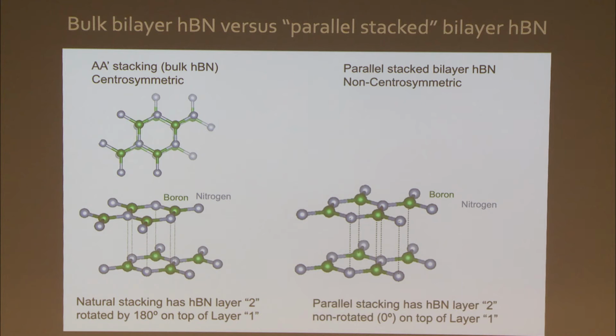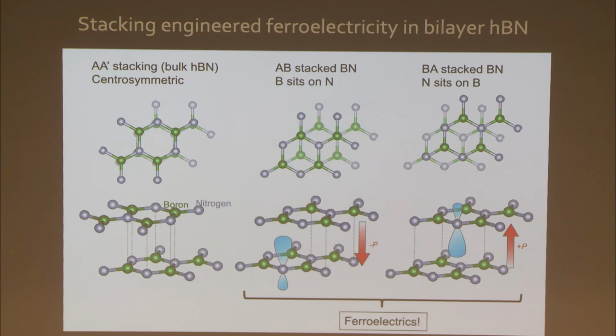Then what happens is that this system becomes non-centrosymmetric, but it's extremely uncomfortable. The boron atoms don't like to be on top of the boron and the nitrogen on top of the nitrogen. So what the system does is that it switches into one of the following 2 configurations, either AB stacked boron nitride, where the boron sits on top of the nitrogen, or BA stacked boron nitride, where the nitrogen sits on top of the boron. And it turns out these 2 configurations have permanent electric dipole moment and opposite with respect to each other. So if I can somehow switch between these 2 configurations, I make a switchable ferroelectric, okay? And indeed, that's what we did, okay?